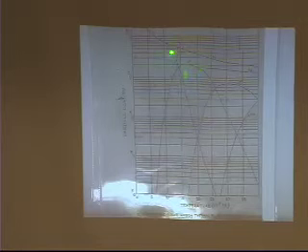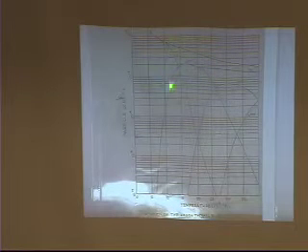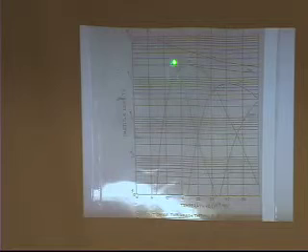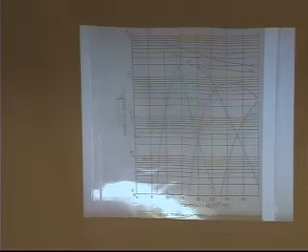We also talked about the fact that welding plasmas are partially ionized plasmas, where I have 5 to 30% ionized. This is the line for argon ions as a function of temperature, and this is the line for argon neutrals. If I'm 5 to 30% ionized, that's going to be somewhere in this region, which is around 11 to 12,000 degrees. And if you measure the temperature of an arc, that's what you get. So everything's self-consistent. Those are some of the things that we actually did cover, other than stories.